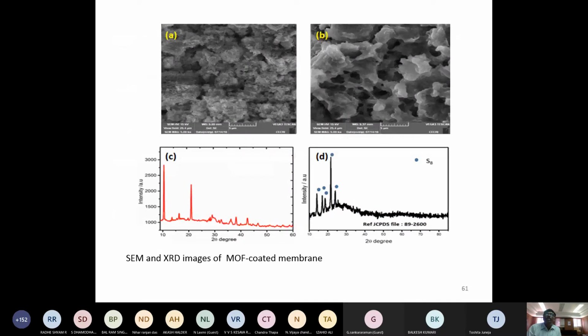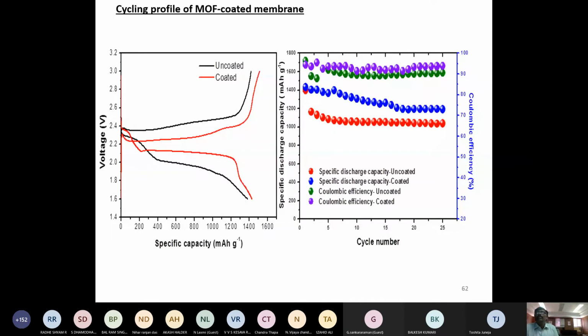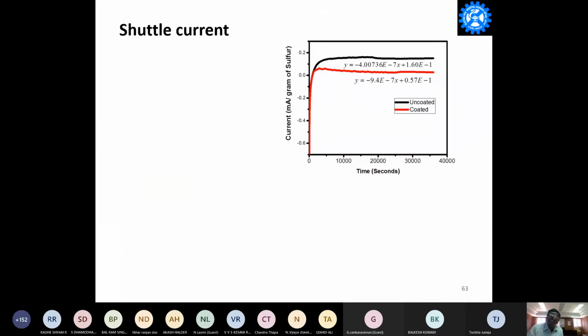For example, we have taken metal organic framework, so we have coated this one, and we have analyzed the charge discharge studies. And the black one is the uncoated membrane. It was able to deliver 1400 milliampere per gram initially, and when we coated with the suitable membrane, metal organic framework, we could go up to 1500, and we have gone up to 25 cycles. All the 25 cycles have exhibited higher discharge capacity than the uncoated membrane.